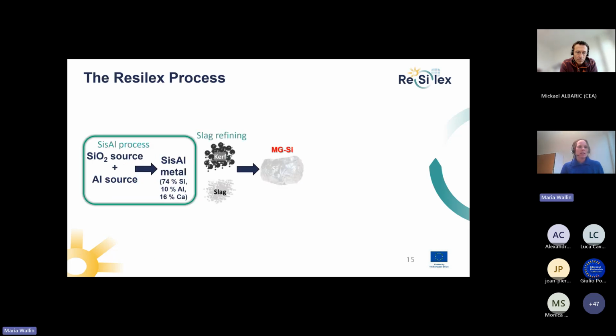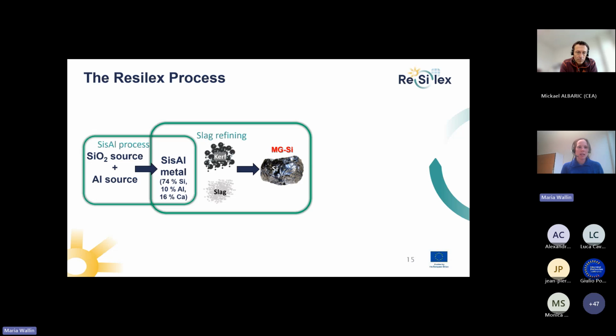And so what we've done then is that we first, in the SisAl project, we produced the SisAl alloy. And as you can see, it's a mix. It has about 74% silicon, 10% aluminum, and 16% calcium. Then we did the refining.